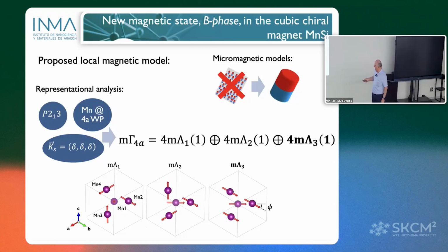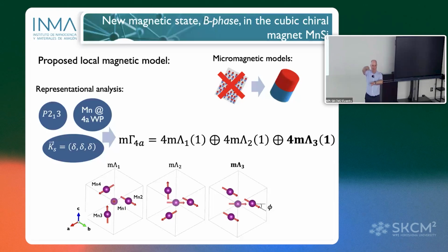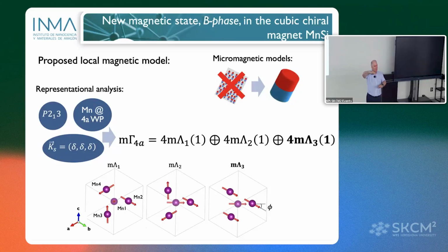Each one of these, this, and this, in this case are parallel, and each one from one layer, from one unit lattice to the other unit lattice, will form a helix. In this case, the three helices will be ferromagnetic, and the other atom, this one, will form another helix with the same period, but with a shift with respect to the others.